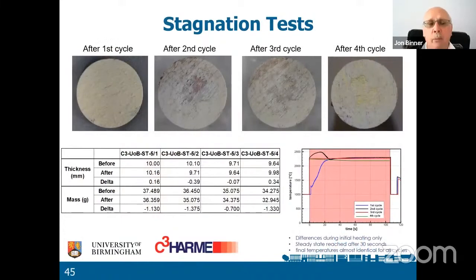And we had one sample, we tested it 4 separate times, up to the first, the second, the third, and the 4th cycle. And you can see this sample is doing fine. It's surviving 4 separate cycles here. And then each time the thickness was measured, the mass was measured. And what you've got there, that plot in the bottom right-hand corner, is how the temperature changes as a result of time. And you can see it really, really uniform. There's a bit of variation in the first 20 seconds, but then after the second cycle, the material settles down and it just performs beautifully.